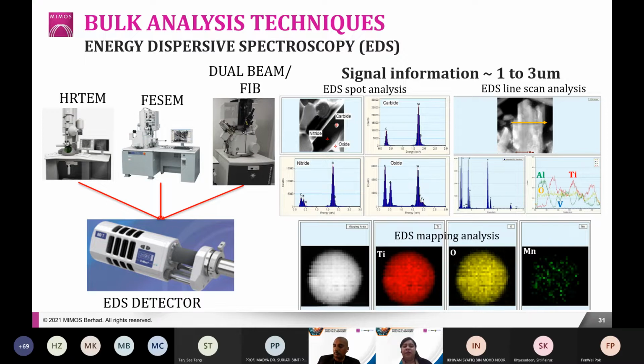And then EDS mapping analysis basically is for failure analysis. For example, if you want to do the mapping in terms of the concentration of the elements, it comes out in colors, so you can identify where the abnormality is, as I said just now, that it has copper on it. So it will give a very nice mapping showing that there is copper present and what the other elements are as well.